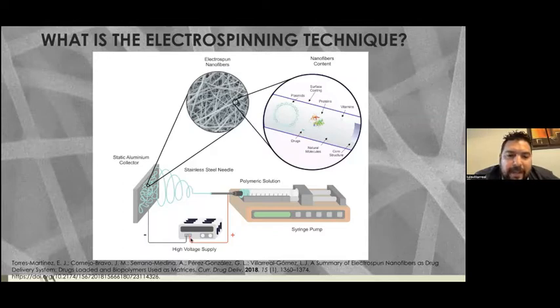Then when you apply the high voltage and you inject the polymer solution, the polymeric drop in the needle gets attracted to the collector and the fiber is created in the air. The solvent that you use to dissolve the polymer evaporates, and the fibers are collected randomly on the collector. So you will have a three-dimensional structure that you can see in this image.